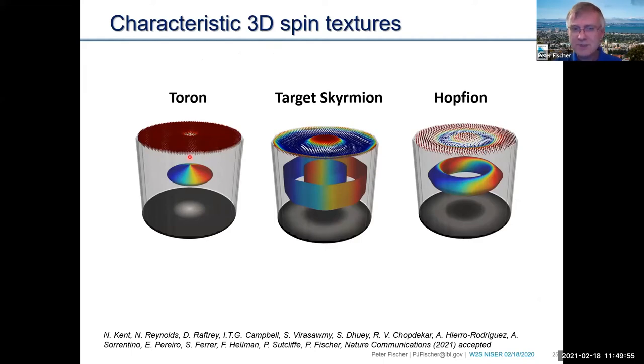And this is just some simulations. The nicely colored structure here is a contour line of the magnetization inside. Then what we did is we combined: up here, this is what a PEEM image would look like from a toron, and the transmission one. And here again, the PEEM from a target skyrmion and the transmission. And again, here, this is the Hopfion. So you can see very nicely, these are very characteristic differences, particularly on the PEEM side.